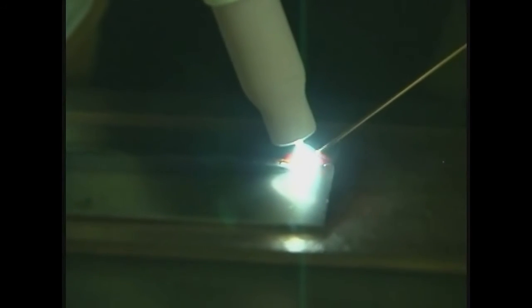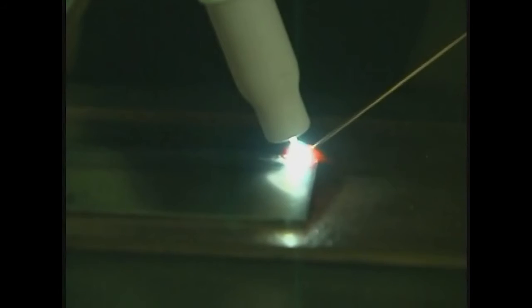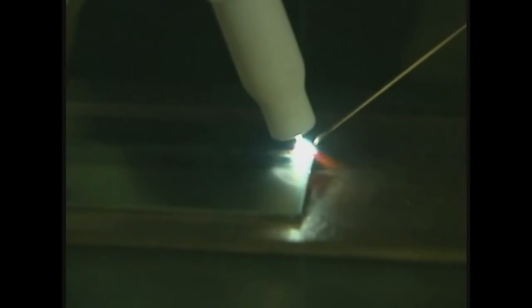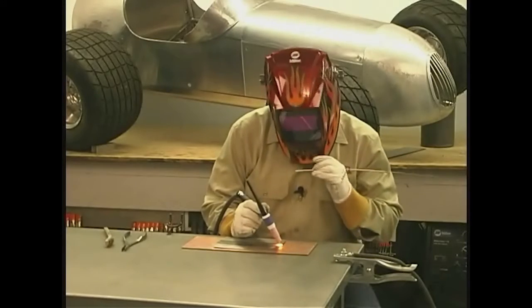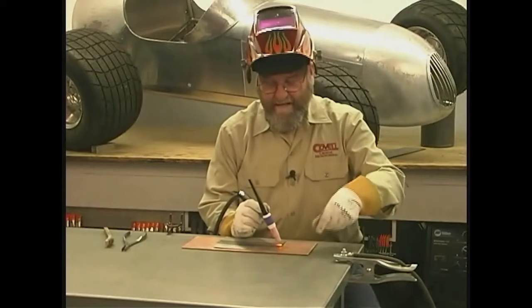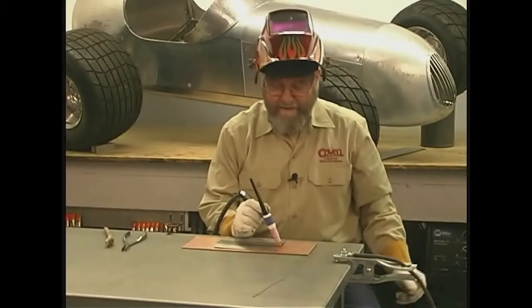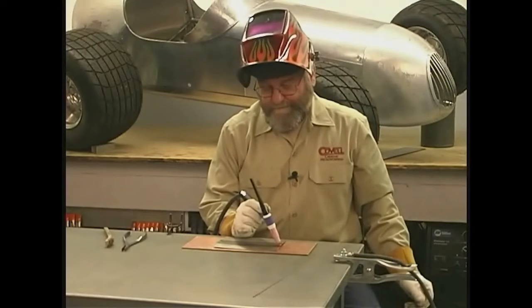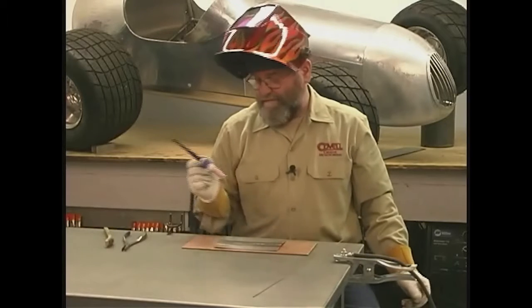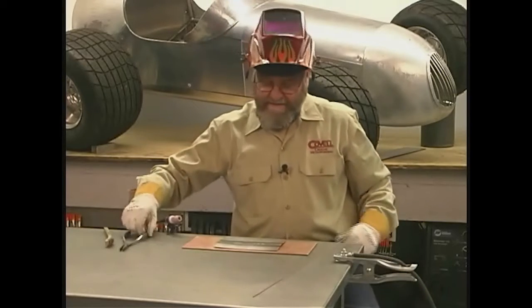As you near the end of the weld, start decreasing the heat with the foot pedal and add smaller amounts of filler rod. The last dab of rod should be placed just before the arc is extinguished. Okay, I'll keep the torch in place until the weld cools. And we'll take a look.